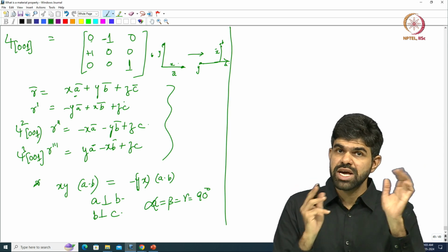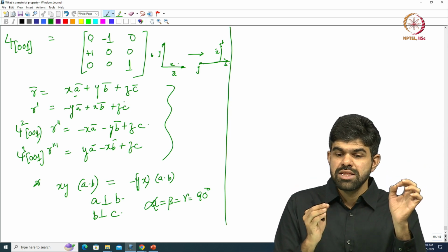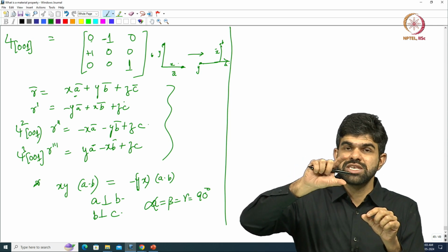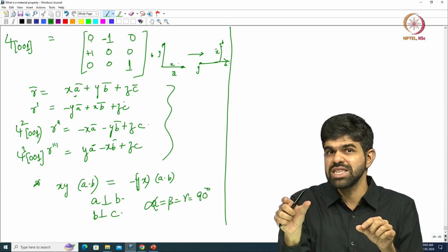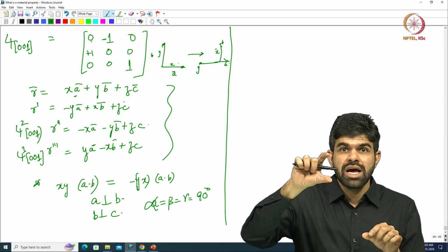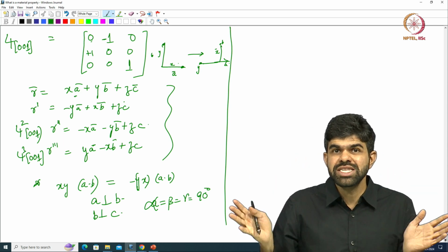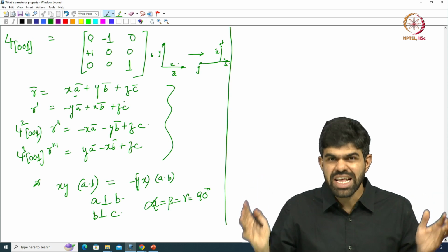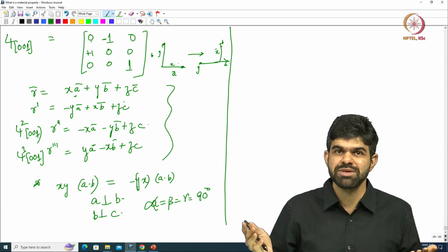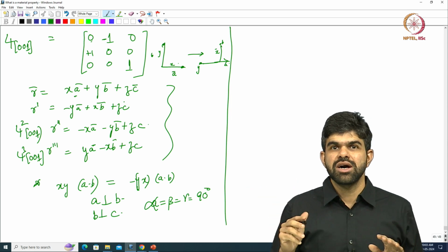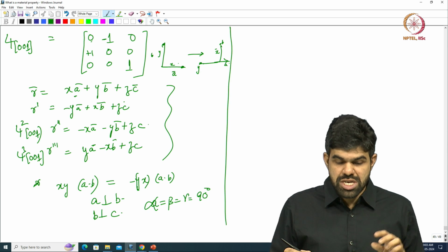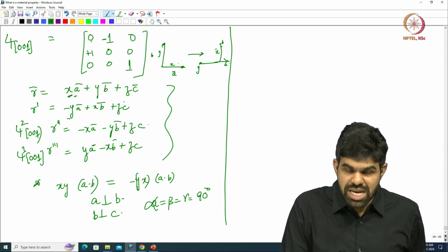Since there is a fourfold axis of symmetry, that means even after transformation the length of the vector here should exactly be the same as the length of the vector there. So, if I say that this is x a, that should be x b, right. Which means that the unit cell vector lengths of a and b should exactly be the same, otherwise you are not going to satisfy the constraints of symmetry, right. So, I am exchanging x and y here, right.